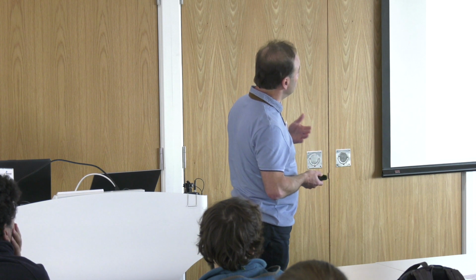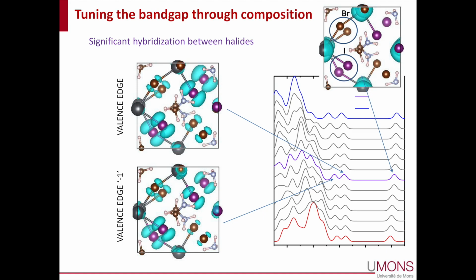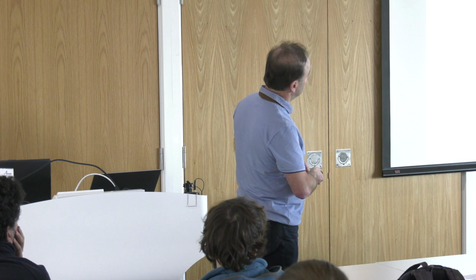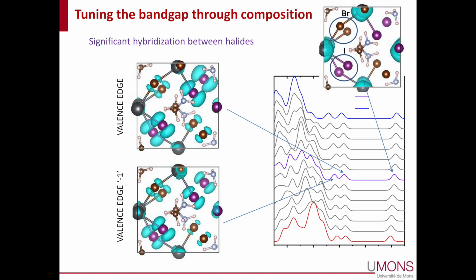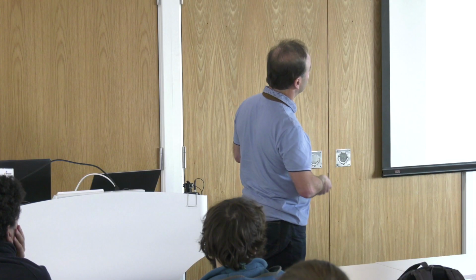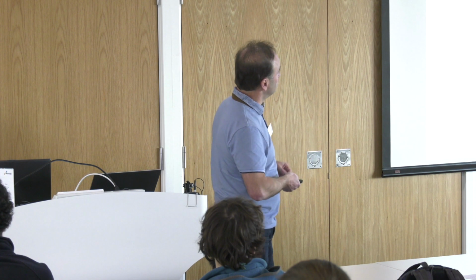And you can tune, of course, the composition as I showed, and look at the wave function. There is another feature, I think, that might not be present in the alloys: even though you have a 50-50 mixture of iodine and bromine here, you can see that there is contribution on the valence band edge, for instance, on both the iodine and the bromine. So there's still interaction, hybridization through the different halogen atoms in the system, despite the energy difference.